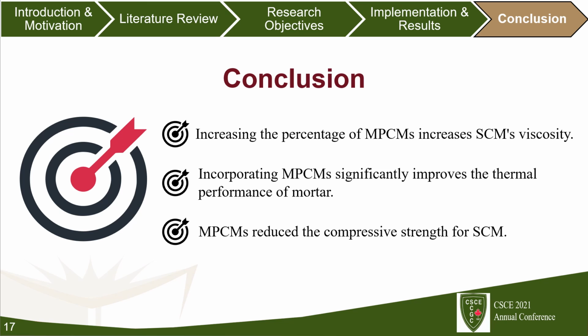So based on the results, it can be concluded that increasing the percentage of the phase change material increases the viscosity of the self-compacted mortar, and also incorporating phase change material significantly improves the thermal properties and the thermal performance of our mortar. And finally, incorporating phase change material up to 3% doesn't affect the mechanical properties. However, increasing the percentage of phase change material in the mortar more than that started to reduce the compressive strength.